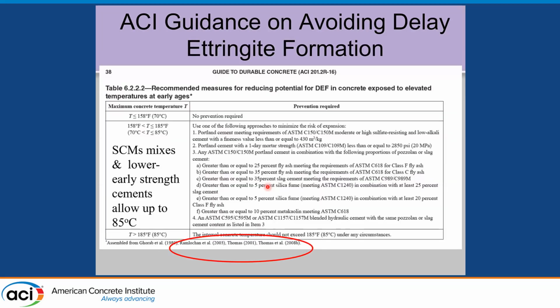So this all led to the ACI guidance. This is out of the 201 guide. There's also, I think, in the 308 guide, the curing guide. And you can see I just circled the names here, Ramlochan's work, plus some of the work we did jointly and some other work that Mike did, are all referenced in this table, which basically says, if you stay below 70 degrees, you don't need to do anything. Between 70 and 85 degrees, if you use alumina-bearing SCMs or ternary blends, you can use them.